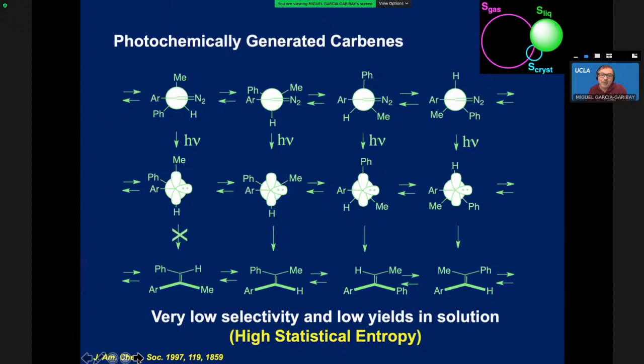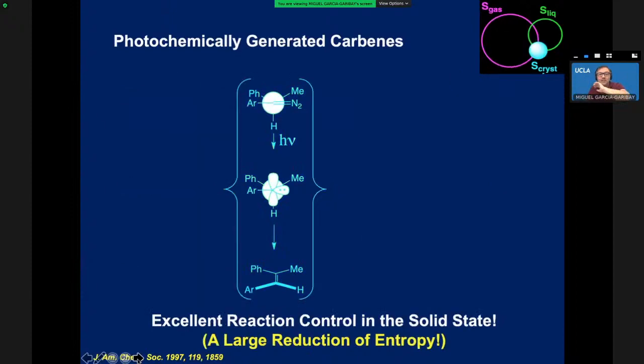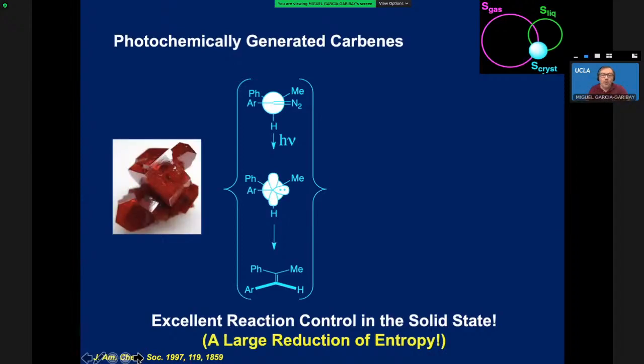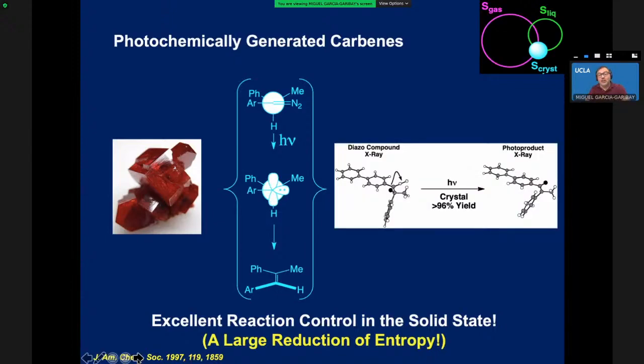So what's going to happen when we have a phase transition and we go from the nice big green circle to, say, a blue circle? We have a large reduction of entropy, right? So what the crystal has done for us is reduced the statistical entropy, selected the system so that we can have 1 diazo compound that goes to 1 carbene and 1 product. So what our beautiful ruby red crystal does for us is make our system much more tractable, more understandable, and really chemically more well-defined. So that when we do the reaction in the crystal, we can see that the crystal structure of the diazo compound correlates beautifully and uniquely with the crystal structure of the photoproduct in a least motion pathway. And we can do that in over 96% yield.